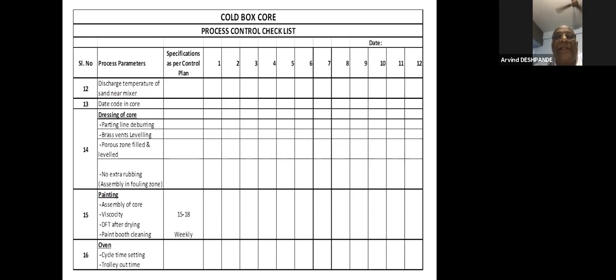Then comes painting, assembly of core, viscosity, DFT, paint booth cleaning. Paint booth cleaning is basically most important. It has to be done weekly because a lot of paint settles and it has to be cleaned. Though the stirrer is there, every week we have to clean it. Then oven, cycle time, setting, trolley out time. As per the size and weight of the core, the cycle time of the core drying oven is important. It may vary from foundry to foundry, but that has to be checked.